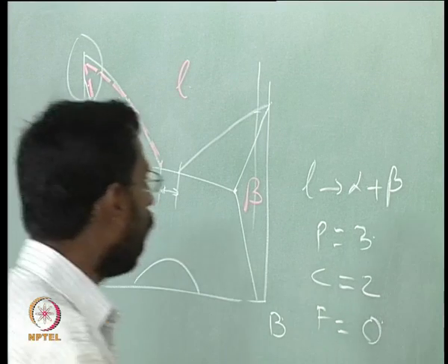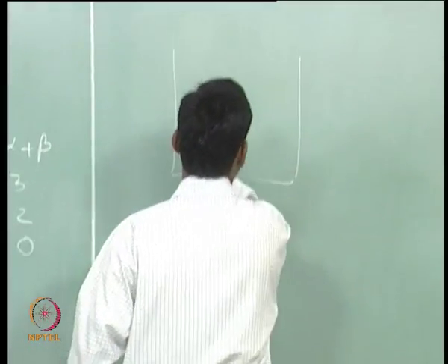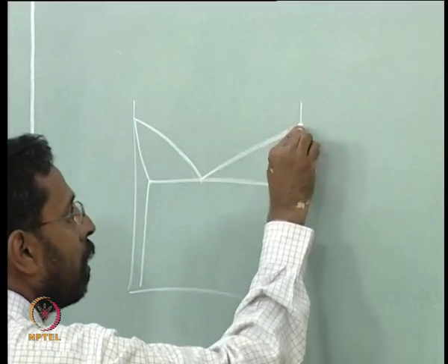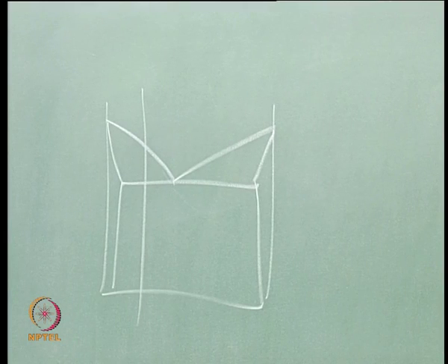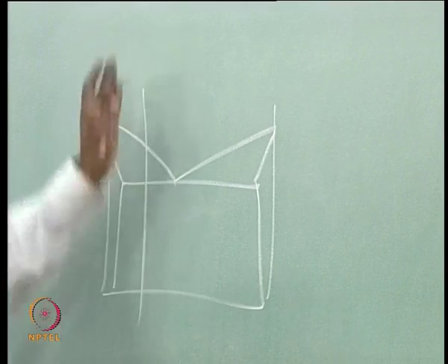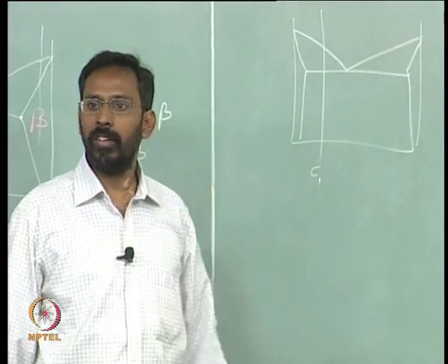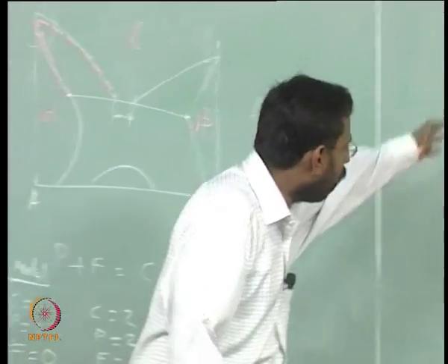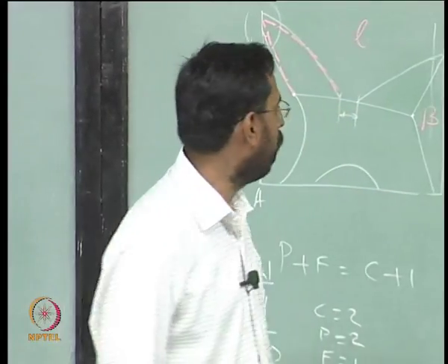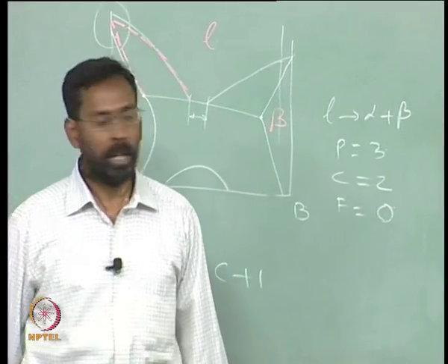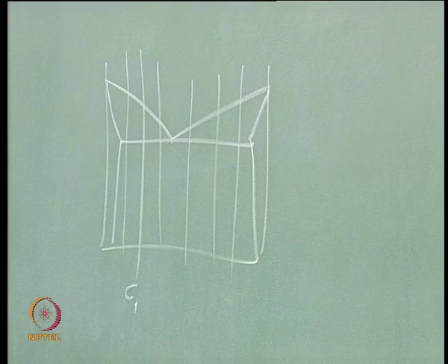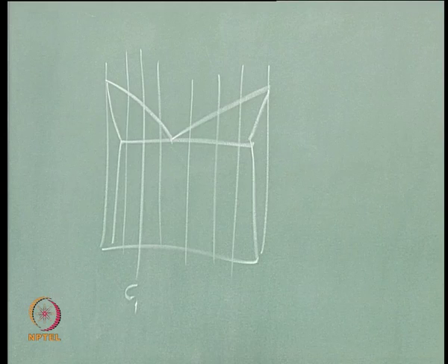And that is the reason why I told you earlier also, for example, if you ask me what would happen if I choose a hypoeutectic composition, where the alloy composition that I am starting with is different from the eutectic composition, then how do you say, sir, that there is a eutectic reaction taking place in this alloy? How do you say that liquid can have only one single composition? In principle, I can choose any alloy here, here, here, here, all of them will undergo eutectic reaction. Am I right? From this point to this point, every composition will undergo eutectic reaction, but incidentally, in all the compositions that you are choosing, the liquid that undergoes the eutectic reaction has only one single composition, that is this.